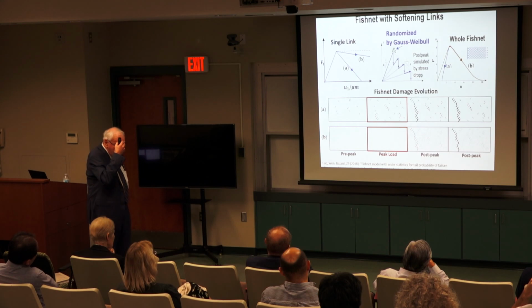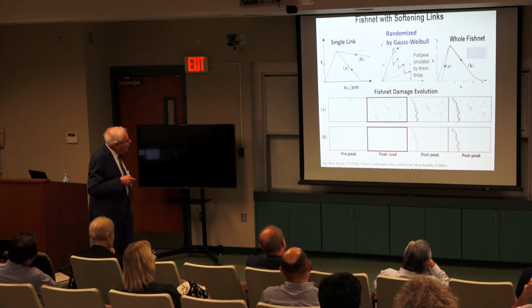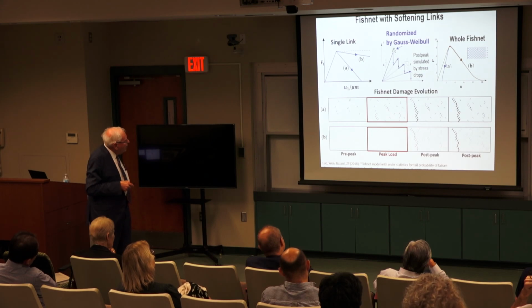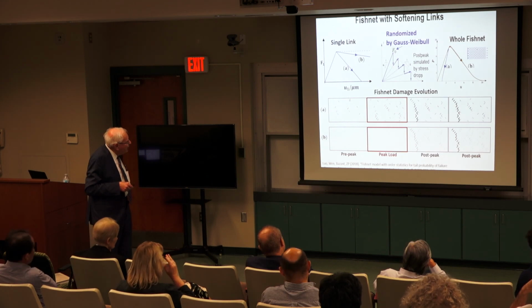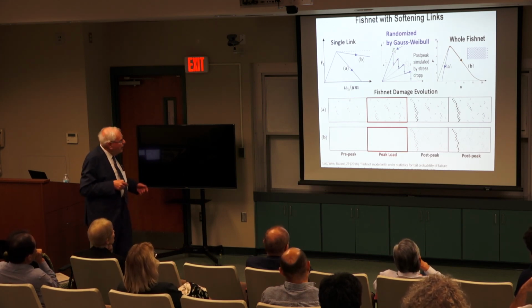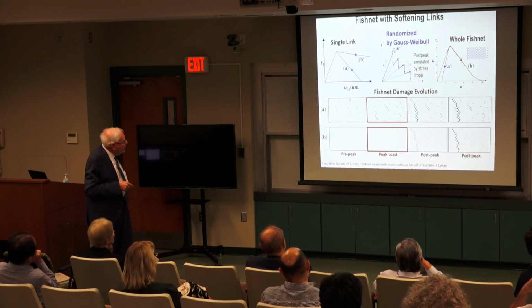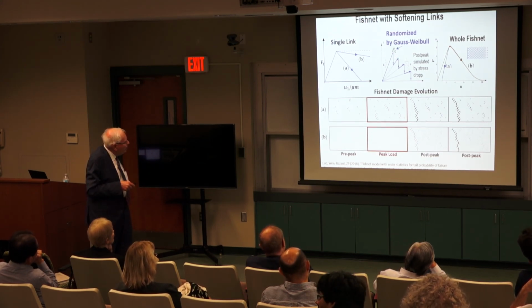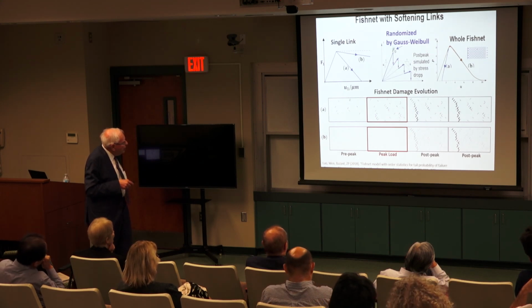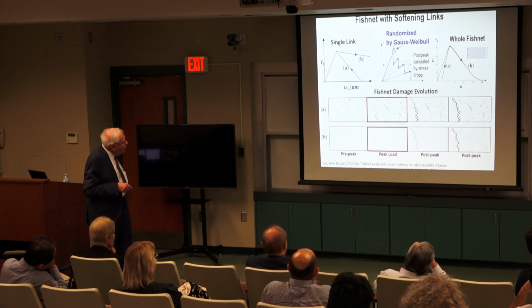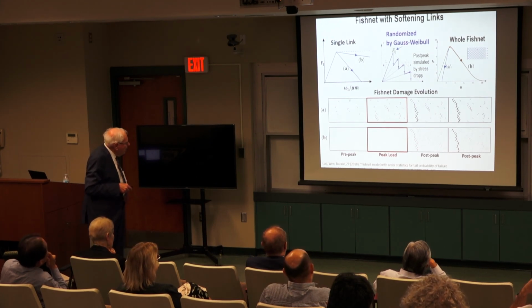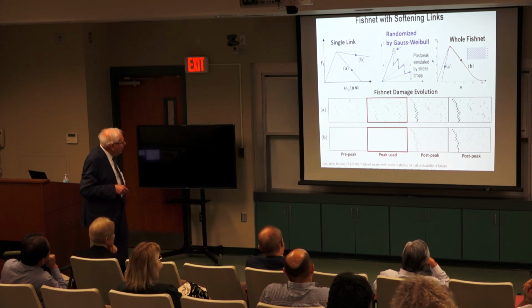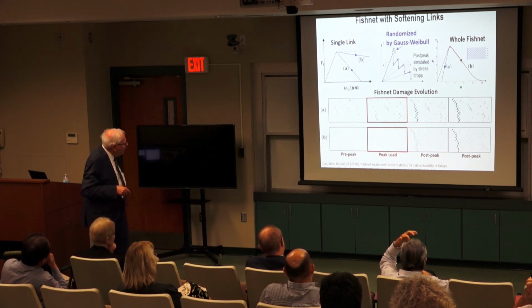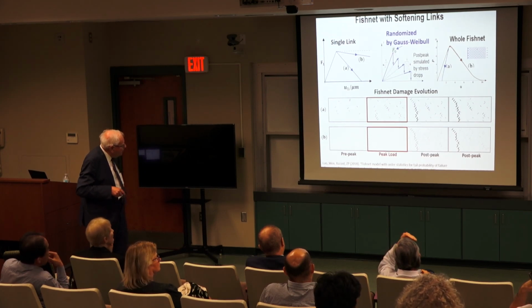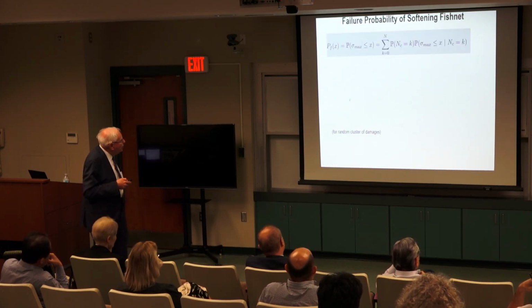All right, so one needs a somewhat different approach. This previous analysis would not quite hold. So what we do, we assume the link goes down, but it goes down in a series of jumps. And that greatly simplifies the analysis. Typically maybe 20 jumps. So jump down, you can reload, get to this curve, it becomes dynamic, and so forth. So a series of jumps. And then the whole fishnet produces behavior like this. And that changes depending on whether you have a vertical drop or not. It changes the behavior very much. In one case, a distributed damage, you know, and goes suddenly. And how to approach this?